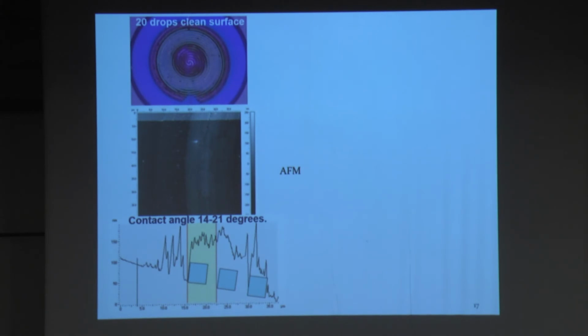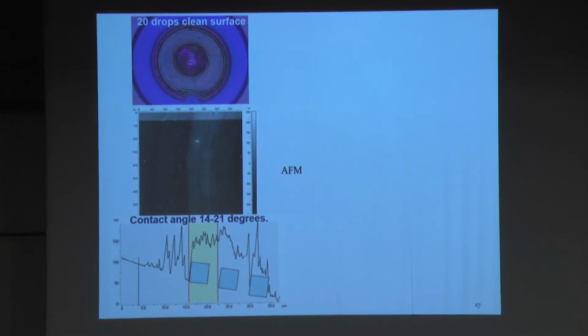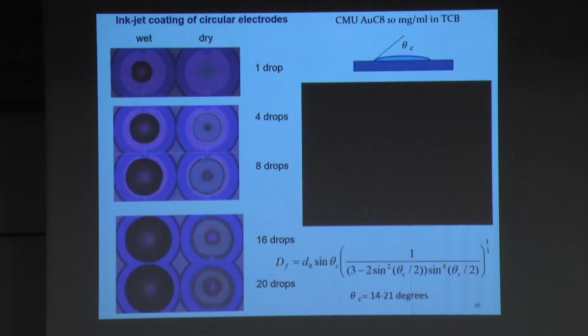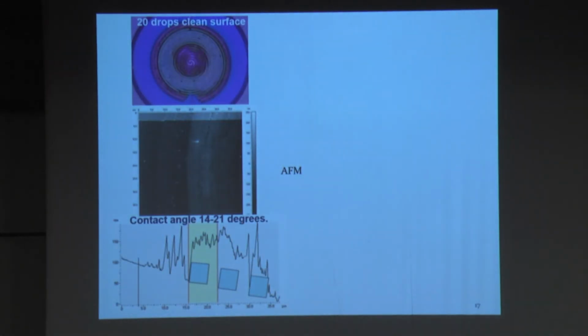When we put more solution, when the volume of the drop is larger than necessary to cover the whole area, the wet splat actually extends beyond the electrodes and goes also to the silicon dioxide, but then it contracts and covers the electrode, forming a coffee ring. On the left side, you can see a coffee ring effect, and on the bottom part, you can see the actual structure.